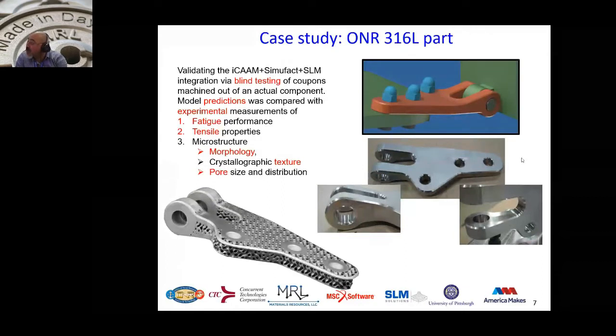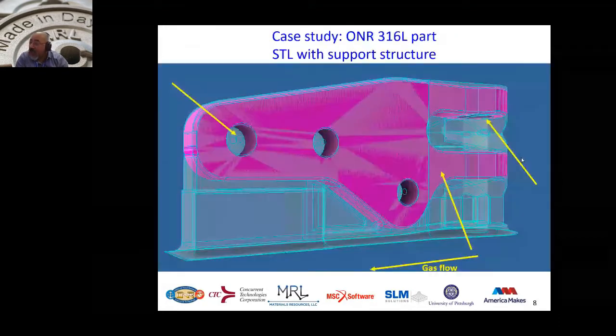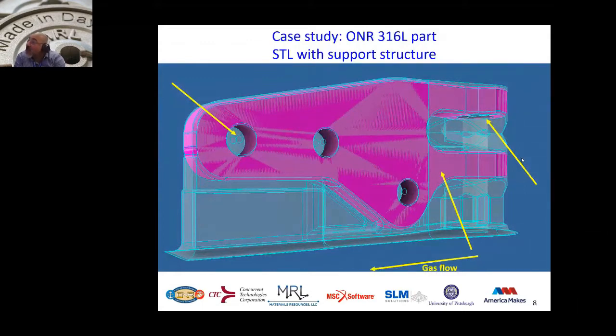And then there is blind testing experimentally done by the CTC team, where they took the part, cut it in pieces, and compared our prediction of fatigue, tensile properties, and microstructure morphology, crystallography, and the pore size and distribution. The slide you see in front of you is the STL that we built at CTC on their machine with our optimized build orientation, as well as support structure that was for additive manufacturability, and later on also for machinability of the part.